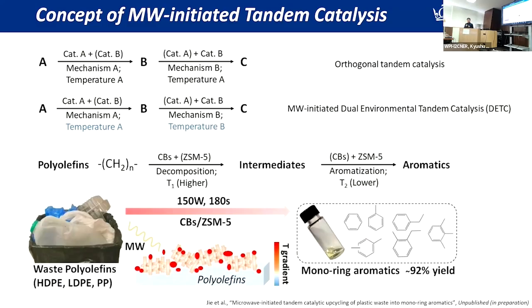But with the microwave, that is different, because if we put two materials inside, we could potentially generate two reaction environments, or two temperatures at different material surfaces. In that sense, we like to call it the microwave-initiated dual environmental tandem catalysis. One successful example we are now running is with carbon black and zeolite. Carbon black is a very good microwave absorber, which will heat up very quickly and efficiently.